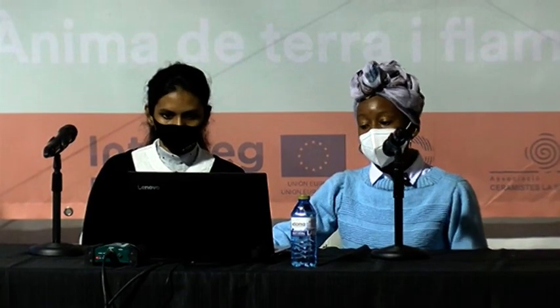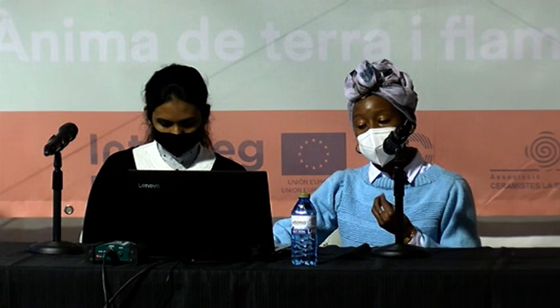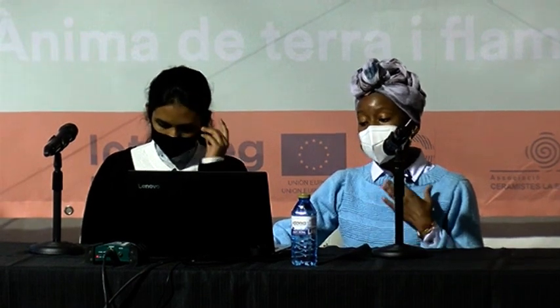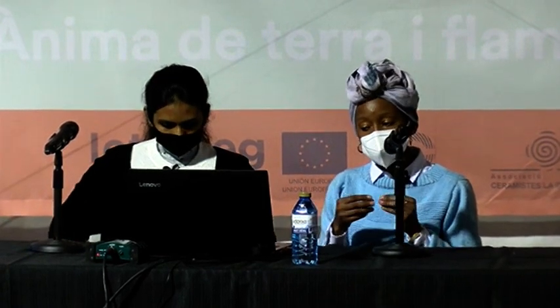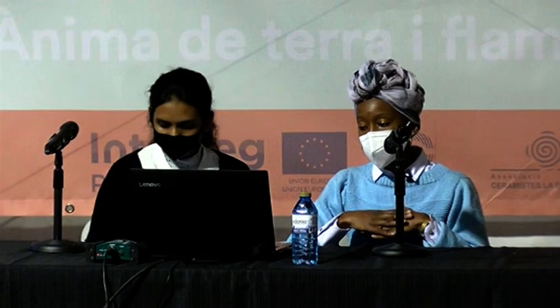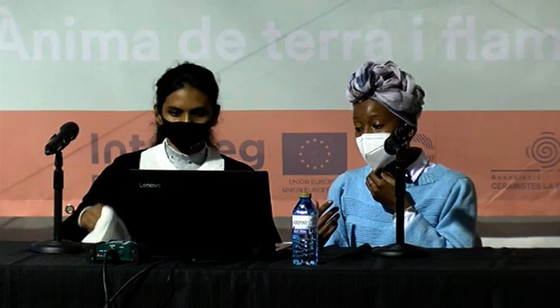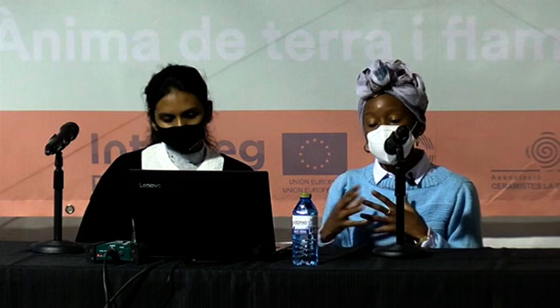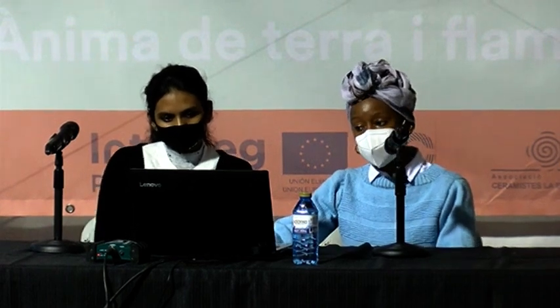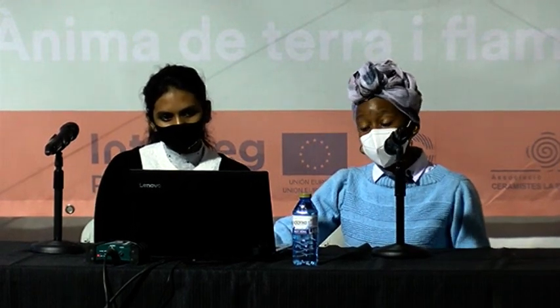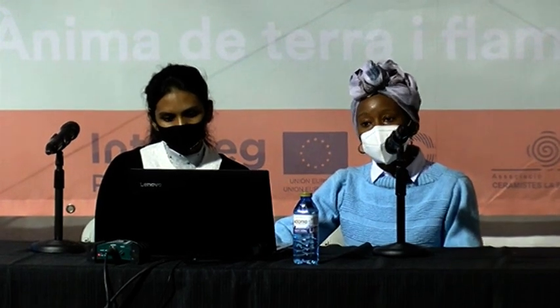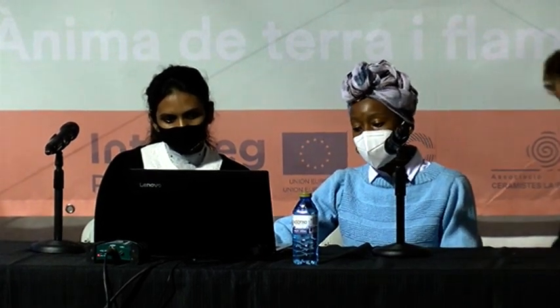Fourth test is a matrix where we mix clay with different amounts of sand in order to test, in the context of 3D printing, how well the material extrudes from the nozzle, how well the layers stick together, how well they keep their shape, and how minimal the shrinkage and appearance of cracks are in the final extruded layer. We do the same with water, where we try to understand how much water works best with clay, and the same with fiber as well. How much fiber do we need in order to create a well-adhered material?